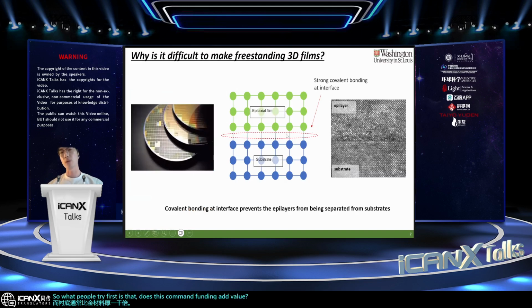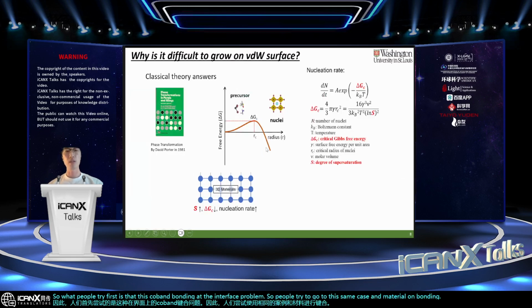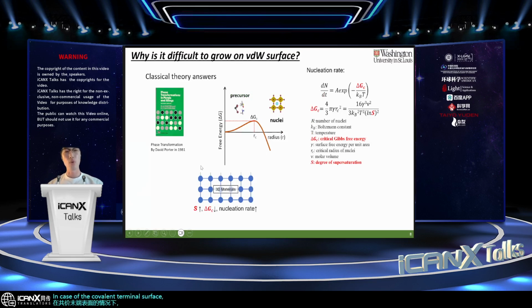So what people tried first was to address this covalent bonding at the interface by growing the single crystal material on a van der Waals terminated surface. But in that case, another problem happened. In the case of the covalent terminated surface, the dangling orbitals are not fully saturated, so thermodynamically it's an unstable state. So they want to make a bond with an additional atom. It means the supersaturation degree on this surface is pretty high, so the critical Gibbs free energy is extremely low. We are able to obtain the periodic potential for the nucleation.